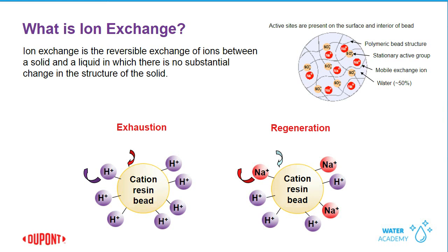If you look down at the center of your screen, the example that I'm going to give is of a cation resin bead. So in this case, our solid that we're talking about is our polymeric cation resin bead. And the exchangeable ions are hydrogen and sodium in this example. So this is a demin application that we're showing here, and the resin starting out in the hydrogen form. And as water with cationic or positively charged contaminants pass through this resin, the hydrogen will be displaced for other ions that the resin prefers, such as sodium. And you can see an example of this in action.